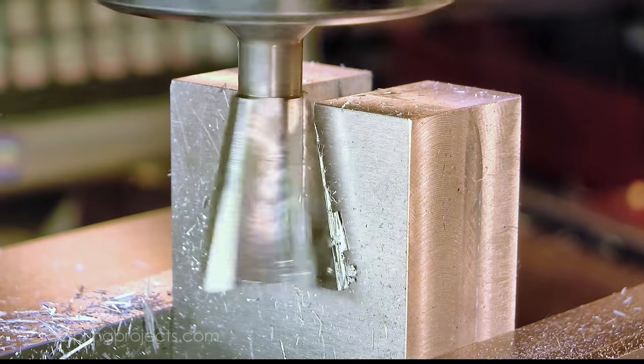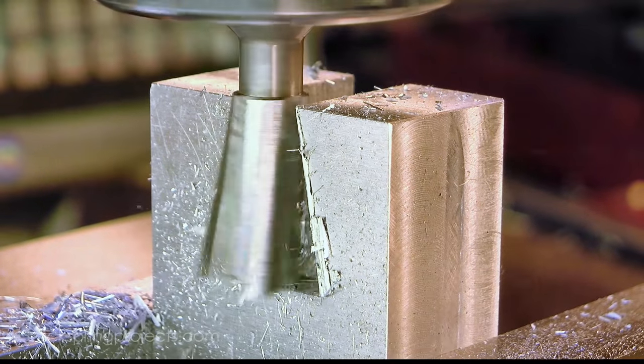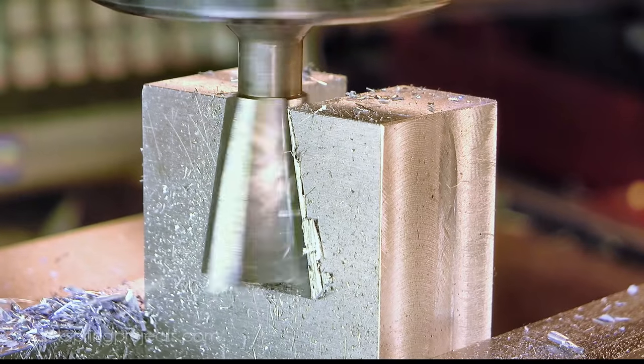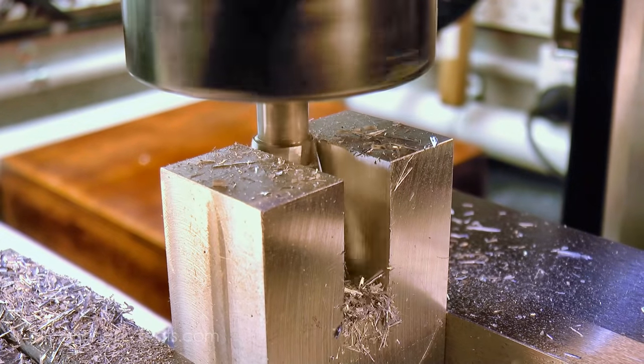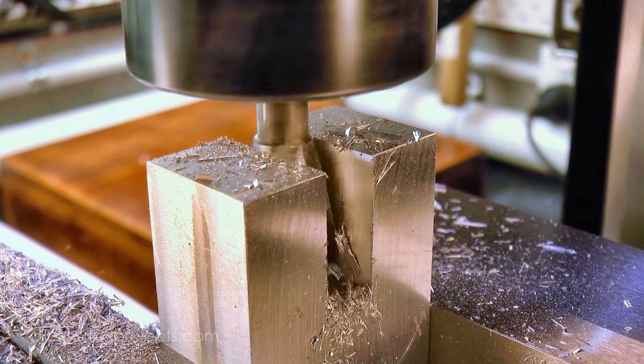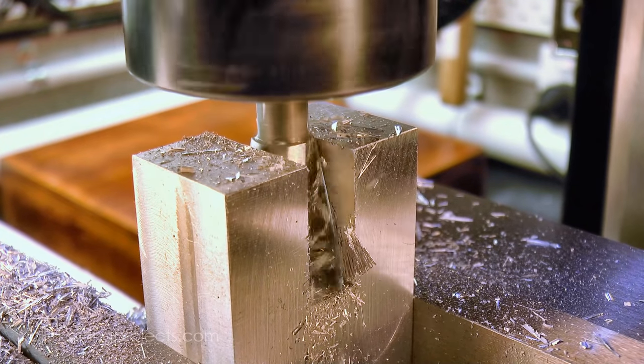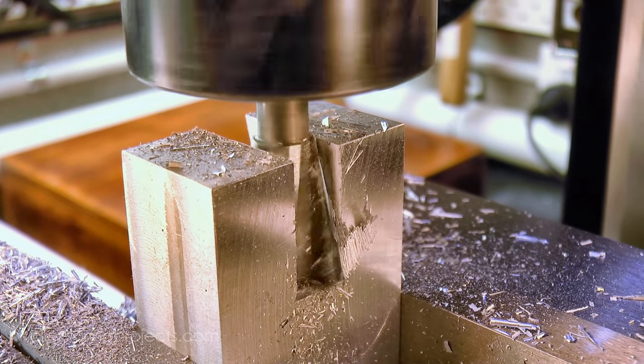As always though, there are some limitations. For one thing, it can't be run very hard. If the cutter heats up too much, the carbon steel will become annealed and immediately lose its cutting edge. It's a light duty cutter, suited to relatively soft materials. The speed of the cut at the top of the tool is also much slower than at the bottom, and the cutting geometry at the top is less than perfect too.